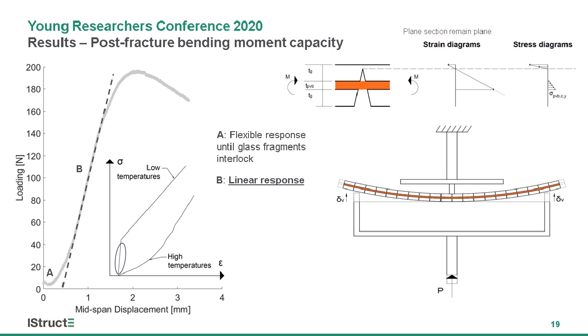The bending moment capacity was derived for this stage under the assumptions of plane sections remaining plane and by applying the transformed section approach commonly used in analysis of reinforced concrete. The compression component is provided by the glass fragments that come into contact as the panel deforms, and the tension component is provided by the interlayer.